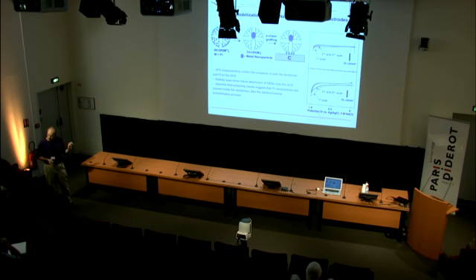It doesn't affect the nanoparticle, because after we've done this attachment, we can analyze the particle again. We can look at the coordination number by XAFS, and it's unchanged. Okay, and then you can do a couple more scans here, and there's no further change. So this cyclic voltammogram is just to show you that something is happening here that attaches the dendrimer to the